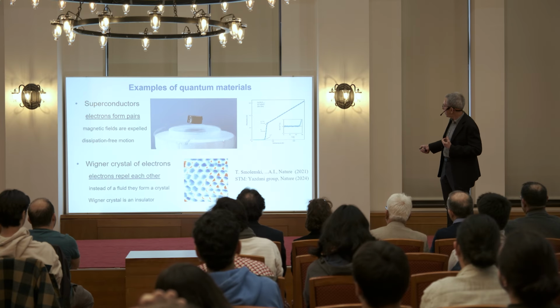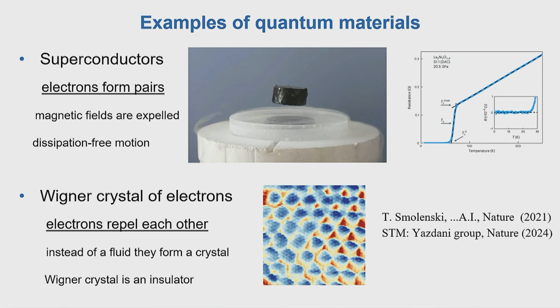Okay, so this is the curve for a lanthanum nickelate, I guess is the name. So this is how the resistance of this material scales as you lower the temperature. You see that the resistance is reasonably small but finite. It goes down with temperature. This is something you expect in metals. I won't go into the details, but at around 70, 80 Kelvin, you see that there's a sharp drop of the resistance, and the resistance value that it reaches is 0. Okay, so the temperature is finite, but the resistance is 0.